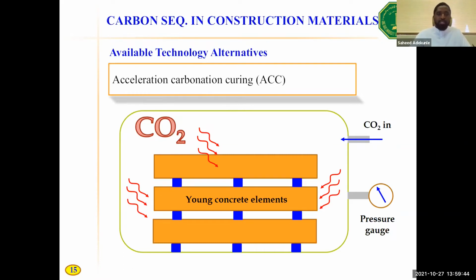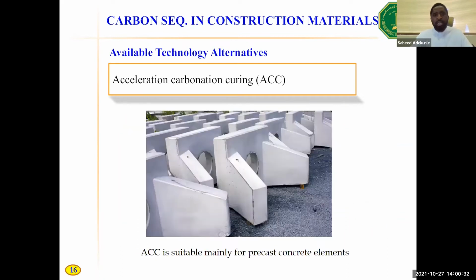And it is important to use this technology when concrete is still young, because young concrete has a chemical constituent, which is mainly calcium hydroxide, or what we call Portlandite. This Portlandite has affinity for CO2 because Portlandite reacts with CO2 to form calcite or calcium carbonate. So this will make CO2 go into this concrete and stay in a stable form. It means our buildings can have CO2 stored in them. And this is going to be a major contribution from the construction industry. However, this accelerated carbonation curing or ACC can only be applied to precast concrete elements.